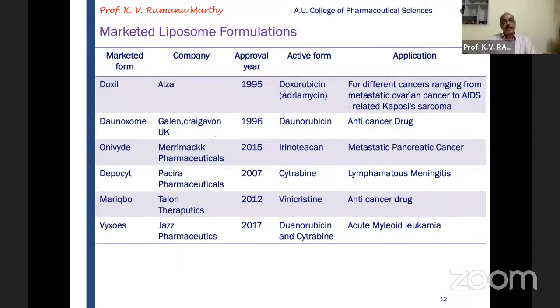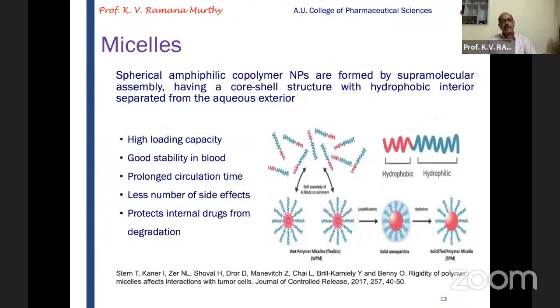Next comes micelles, and they are spherical amphiphilic copolymer nanoparticles formed by supramolecular assembly, and they have the core shell structure with hydrophobic inside and hydrophilic outside. So the diblock copolymers are joined together for the formation of micelles, and these micelles are going to be lyophilized, and when they are hydrated, we are going to have the formation of these micelles.